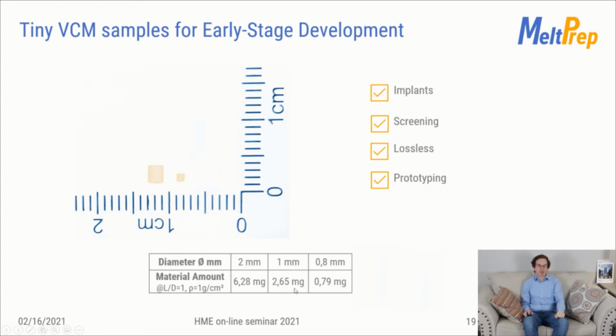For 0.8 millimeter diameter, it's already less than a milligram. If this is still too much material for you, or if you're interested in designing an intraocular implant, one can use our smallest dimensions in the portfolio, which would be 0.5 or 0.3 millimeter. And then you reach down into the microgram range.